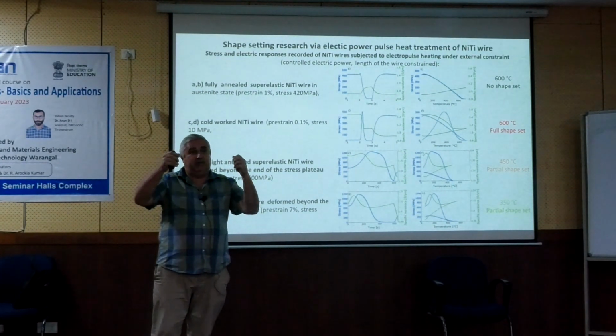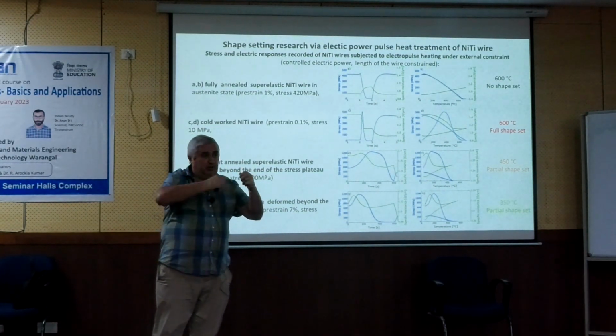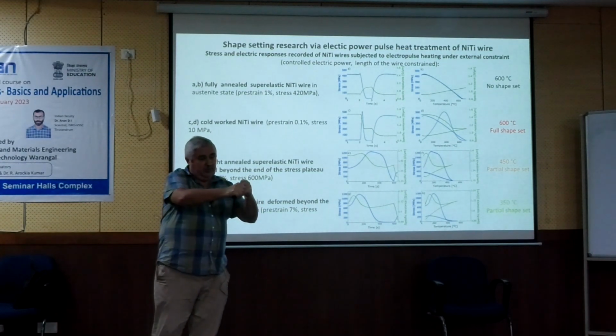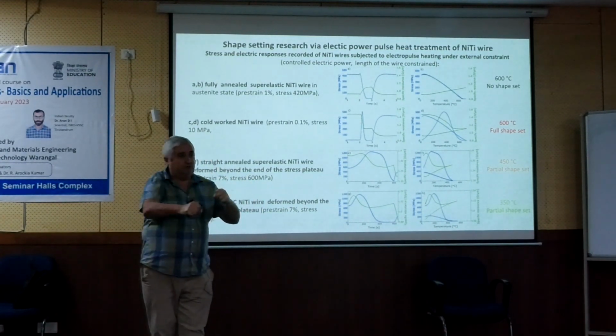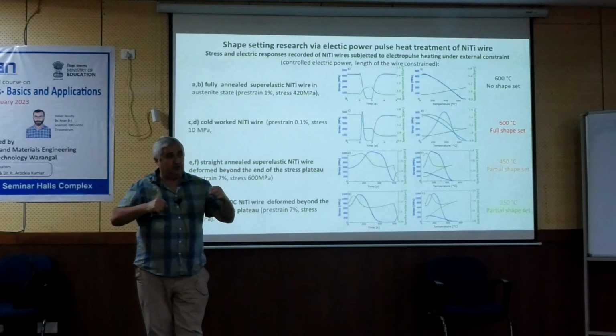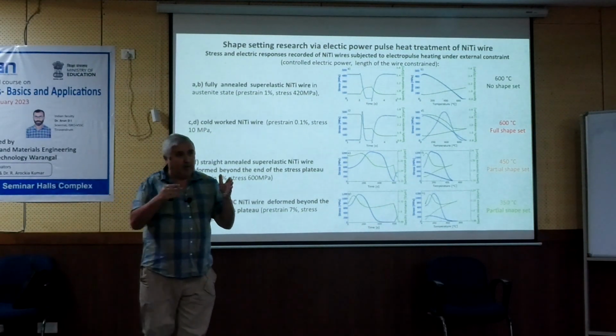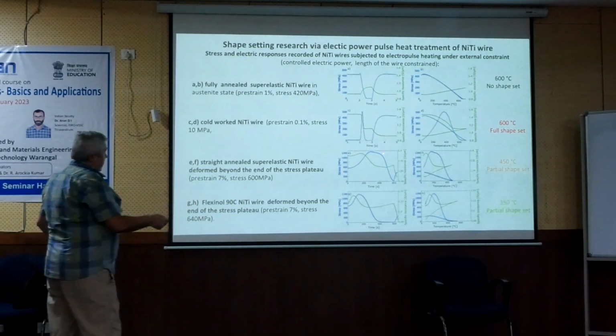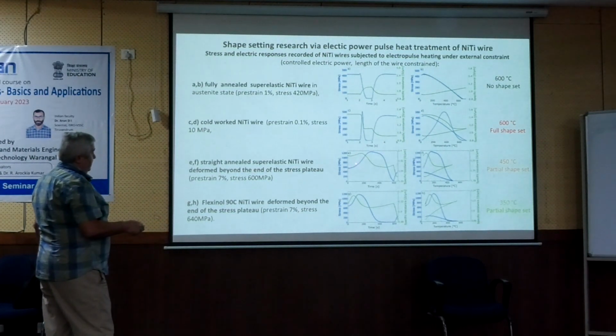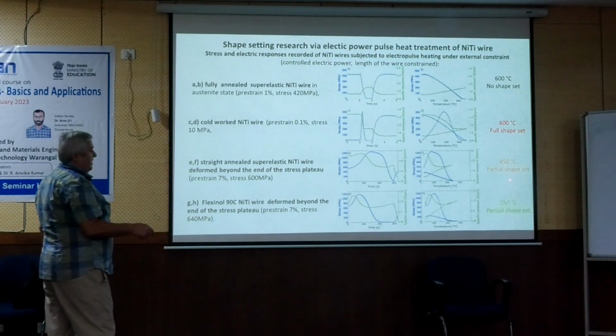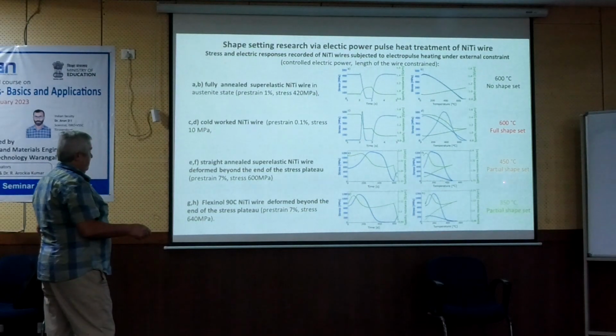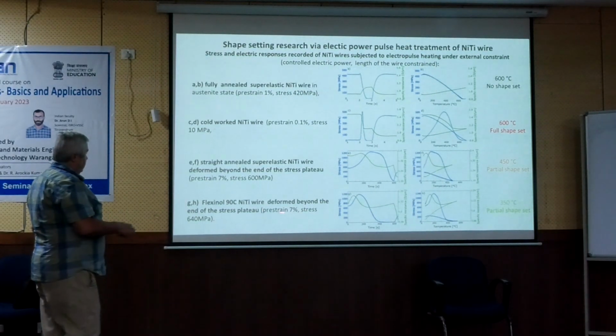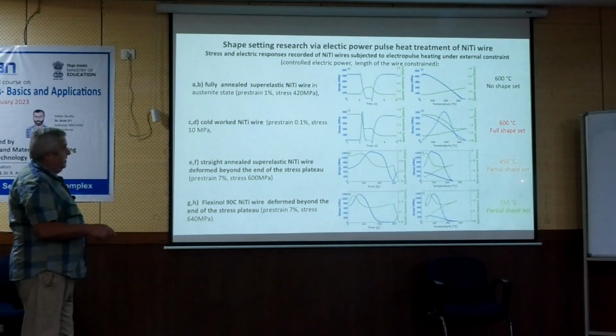So now I have the wire which I put on the coil, but at the same time I stretch it so it's fully stretched into the martensite. So there is martensite in the wire. So now I constrain the martensite, and if I do the heat treatment, the response is similar. It goes up, the resistance goes up and down, stress goes up and down, and I got some partial shape set. You know? This is another wire, similar thing.